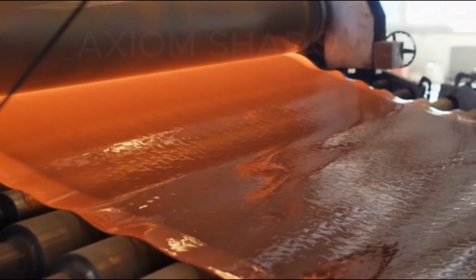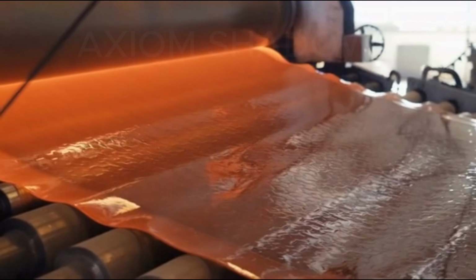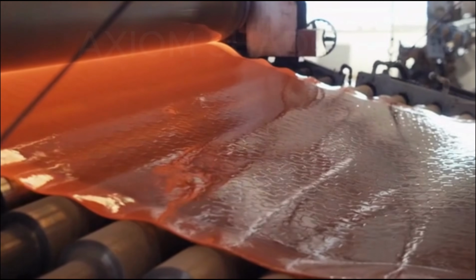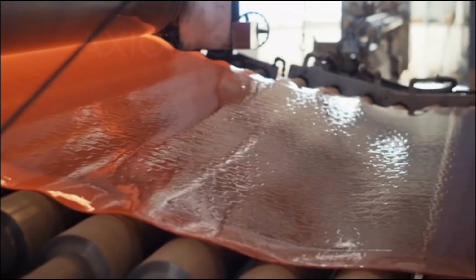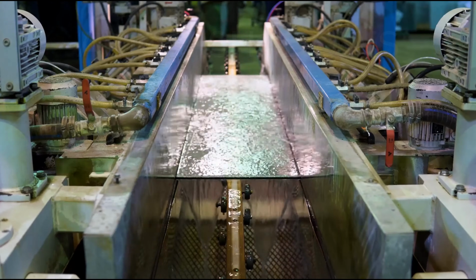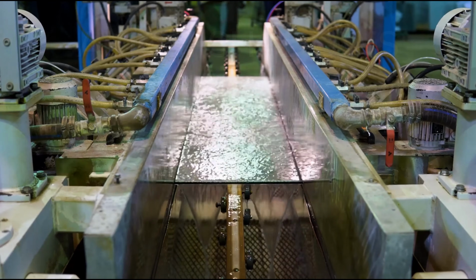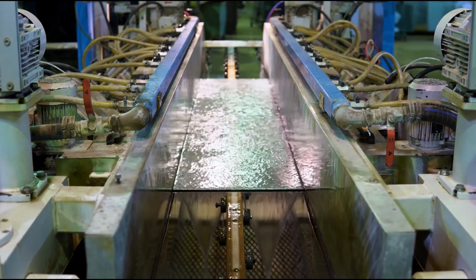Hydrogen and nitrogen gases flood the chamber, keeping oxygen out so the tin doesn't oxidize. The glass floats, glides, and stretches into a continuous ribbon, moving at about 10 centimeters per second. It looks calm, but every fraction of a degree matters. Next stop, the annealing lehr, where the magic of controlled cooling begins.